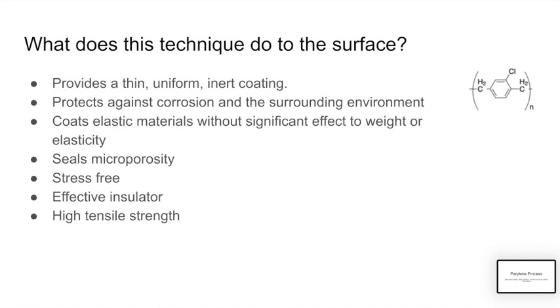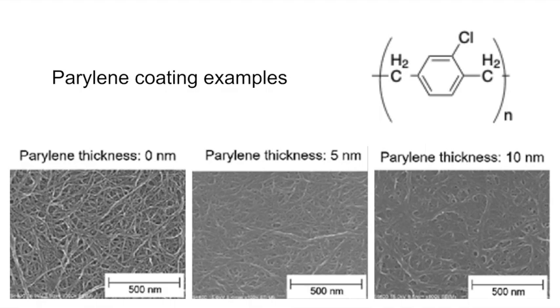Because the formation of the coating occurs at room temperature, the coating is effectively stress-free or resistant to thermal stresses. It is an effective insulator or dielectric, which can be used to coat electrical components, and it also has a high tensile strength. So this shows the chemical structure of a Parylene polymer and also a few SEM spectroscopy photos